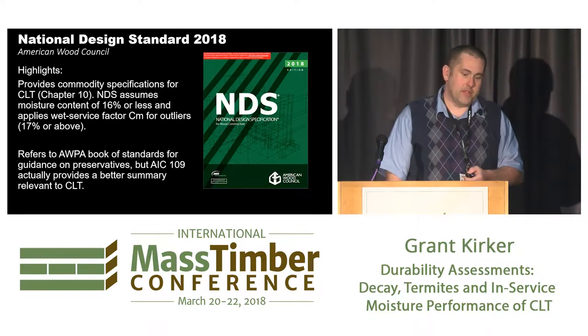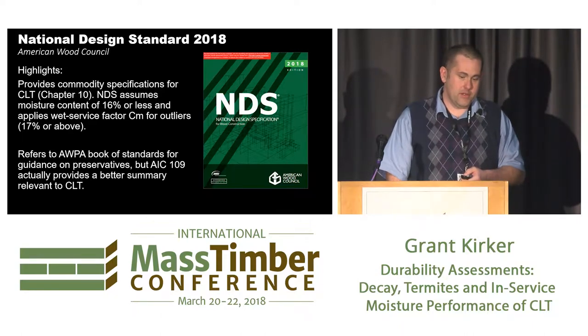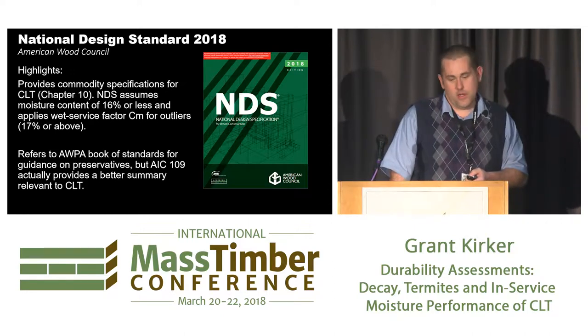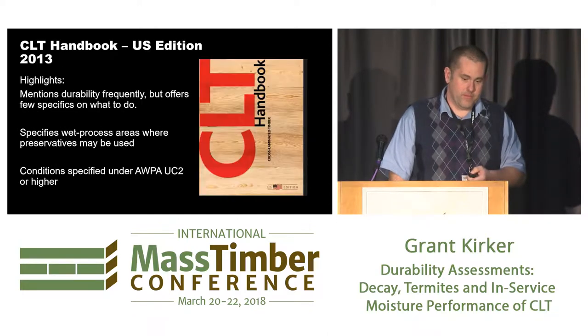A lot of their specifications assume a moisture content of 16% or less, and then they have special correction factors that apply to wet service when you get above 17%. It also refers heavily to the AWPA book standards for guidance, but based on looking at this, I found the AIC 109 actually had more information.